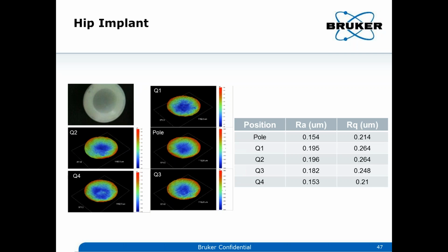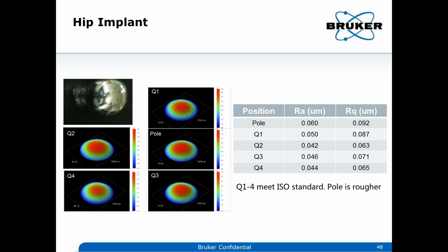So you can see here different steps or different samples. You measure it at different points. So pole is measured at the top of the surface, and then we measure at different points, like Q1, Q2, Q4, and then you can see how the Ra and Rq, that's what we control here, change from point to point, right? So here I actually even show the counter surface.